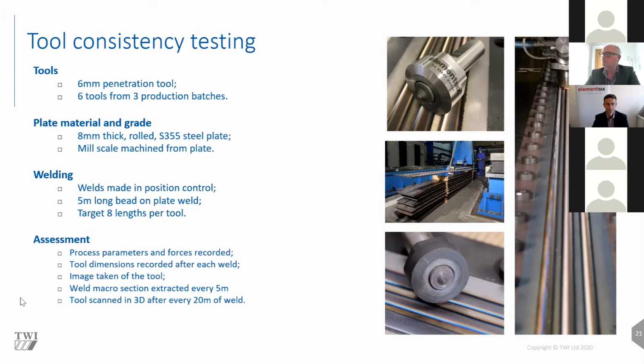For every weld made, we recorded the forces, the torques, and the energy input. We recorded the tool dimensions before and after each weld, photographed the tool, and did a laser scan of it every 20 meters to allow the wear to be assessed.